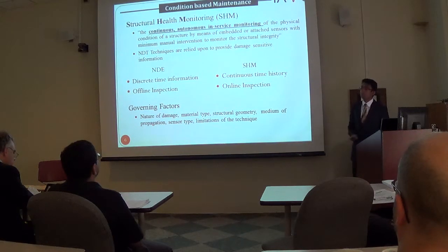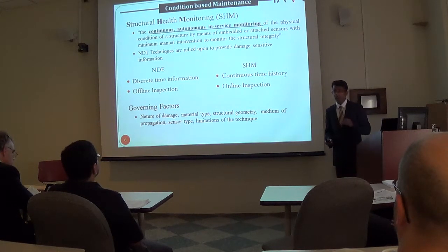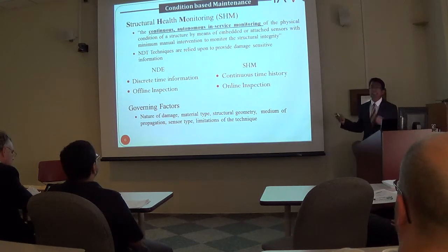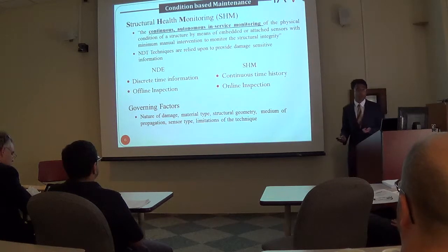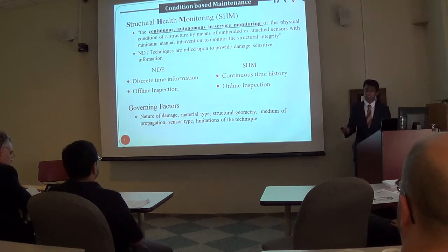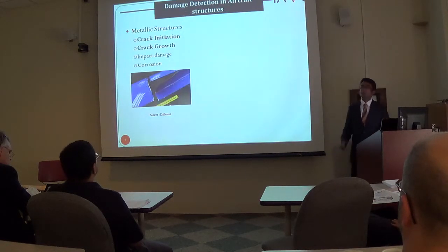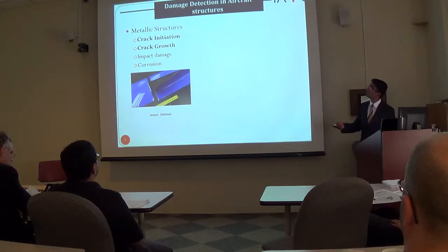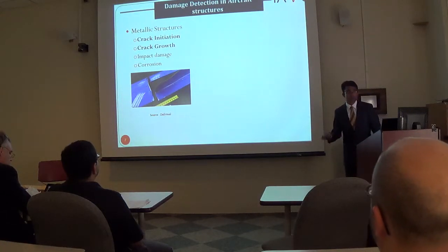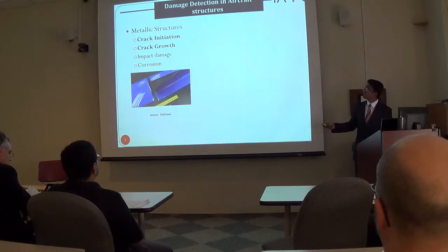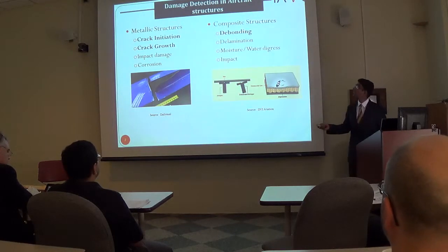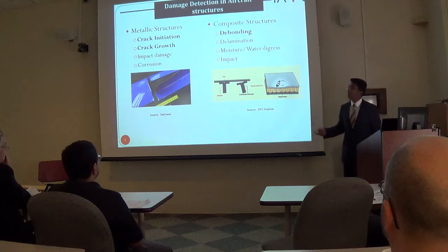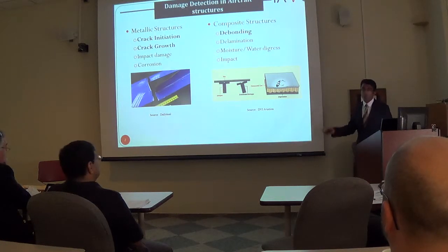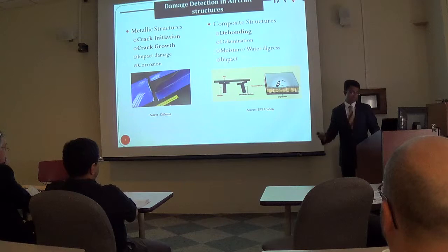Nevertheless, in either approach, in order to optimize the damage detection process, certain factors must be considered, such as the nature of the damage to be investigated, the material type, the structural geometry, the sensors, and also the limitations of the applied technique itself. Some of the commonly seen damages in aircraft structures, for example in metallic structures, range from crack initiation to crack growth to impact damage and corrosion. While in composites, the prime failure mechanisms range from debonding to delamination or moisture and water penetration and other sorts of damage such as impact.